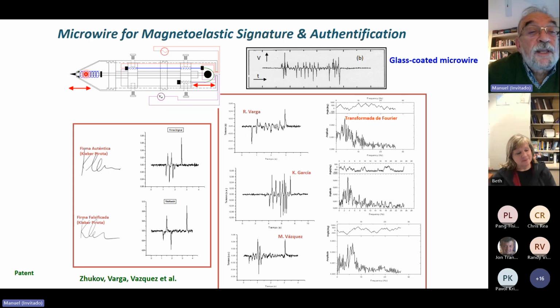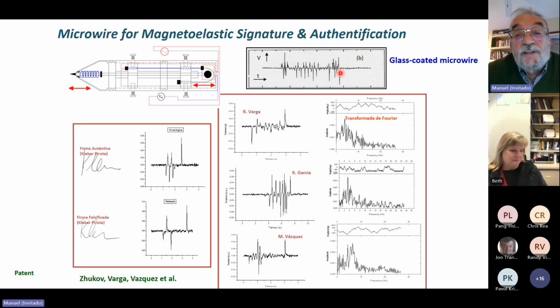Well, it's connected to a spring, and at the upper part and the bottom, we have some cables to measure and characterize the magnetic behavior of the microwire. So when we are writing, when we are signing, we are exerting some mechanical stress on the microwire. Finally, the signal we obtain with the cables is a voltage as a function of time, and we get something like that. This is a typical magnetoelastic signature when we are signing. It is characterized by a number of peaks, positive, negative, and a particular trend.